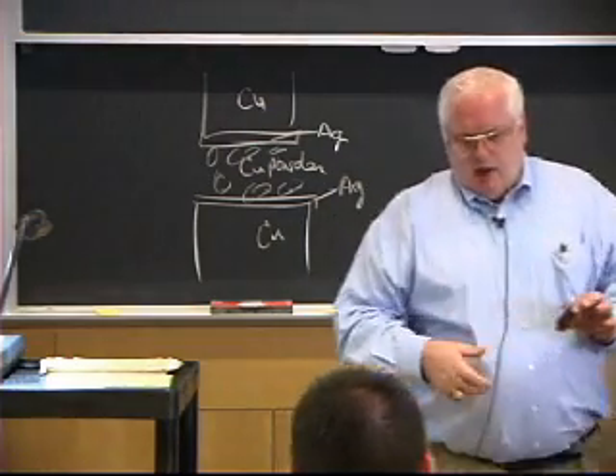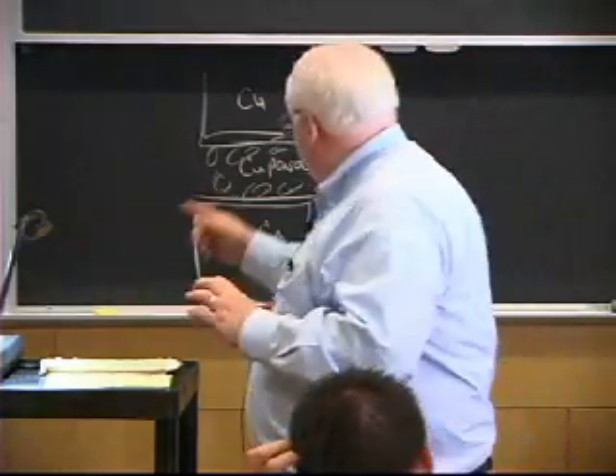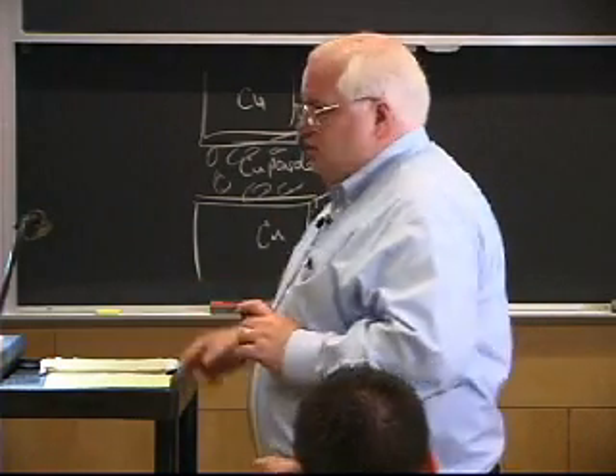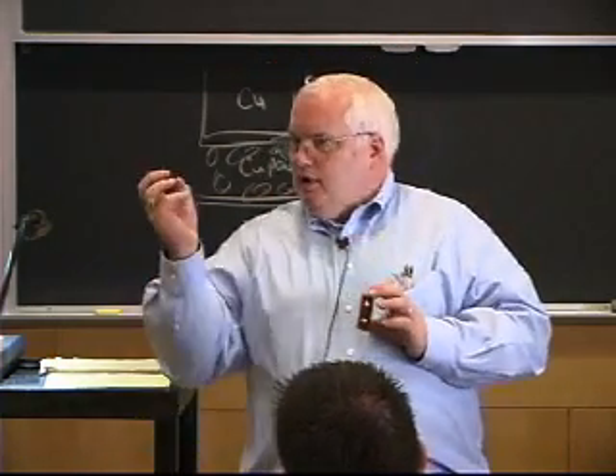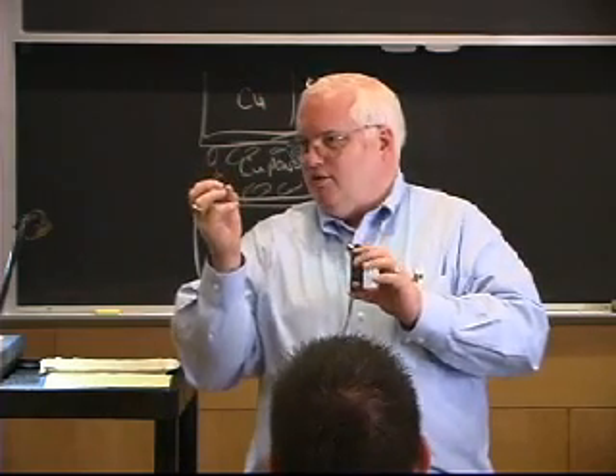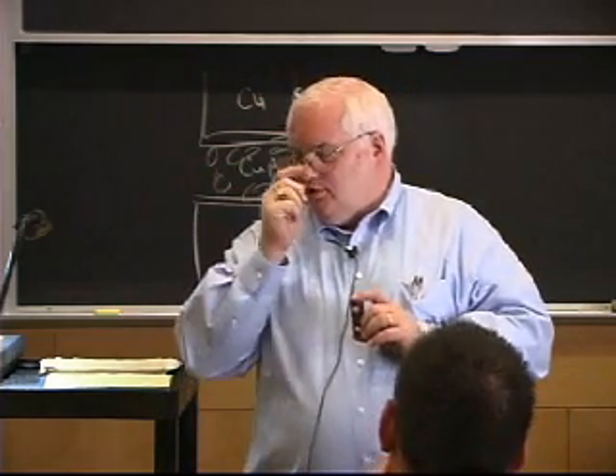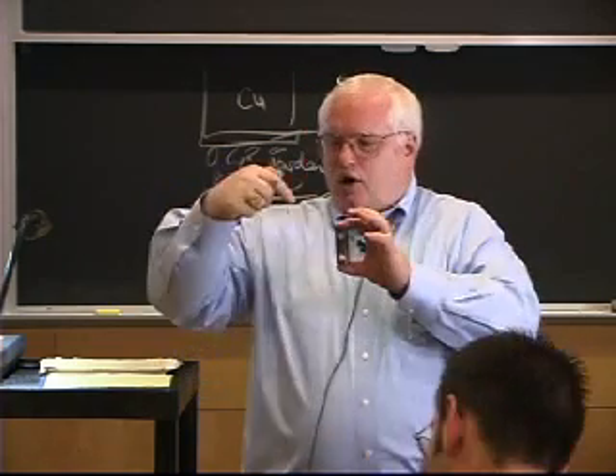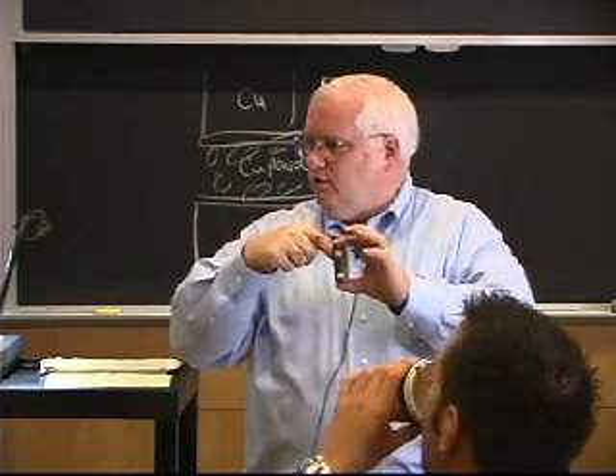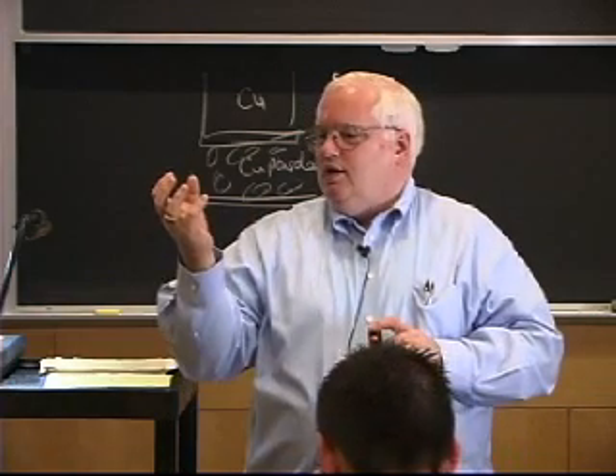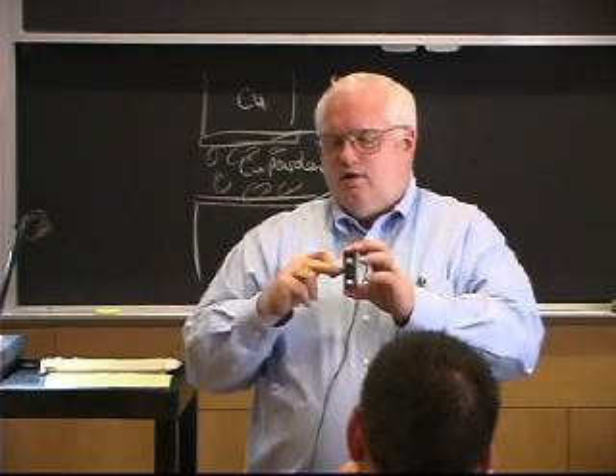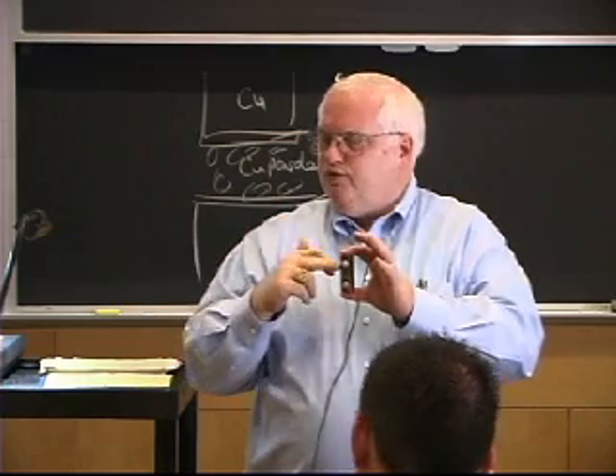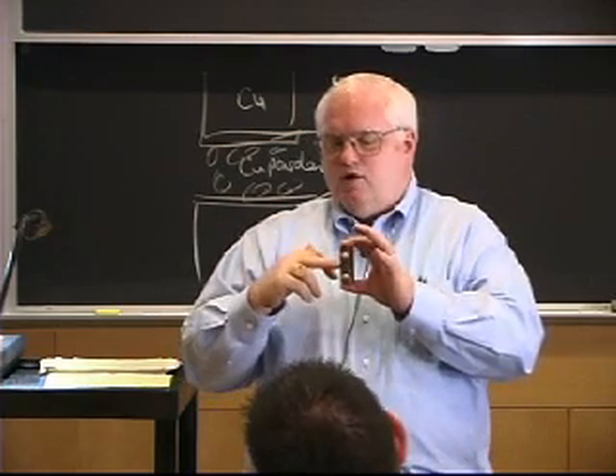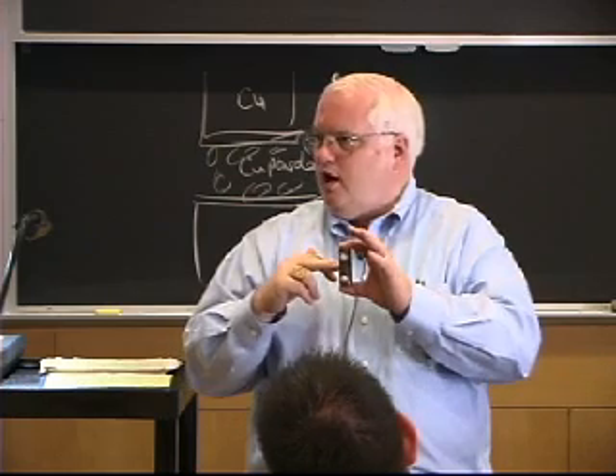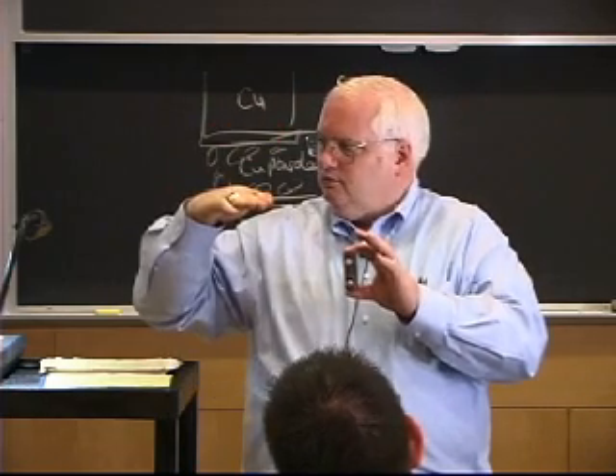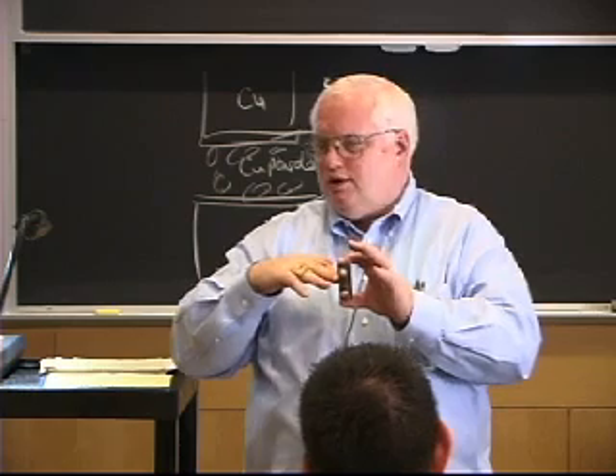Well, it turns out you couldn't infiltrate it very far, because what happens is the silver starts to react with the copper and melts it. And those big copper balls, I mean, they're not very big. They're actually about half a human hair in size, but they get even smaller. And they actually start plugging up the interstices between the ones beneath it. And you can't infiltrate with liquid. If the liquid, like in this case silver, will erode the copper when it starts to melt, you can't infiltrate more than 3 or 4 or 5 powder layers deep from either side, which means you couldn't form a joint more than about 0.010 of an inch thick.